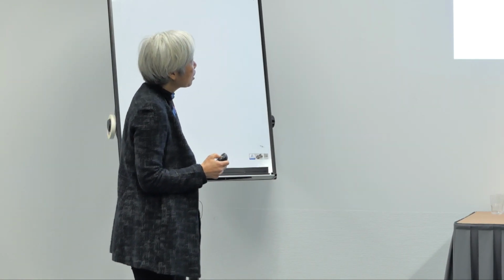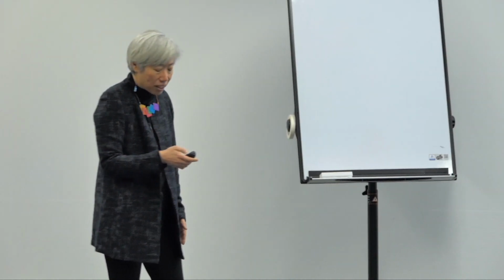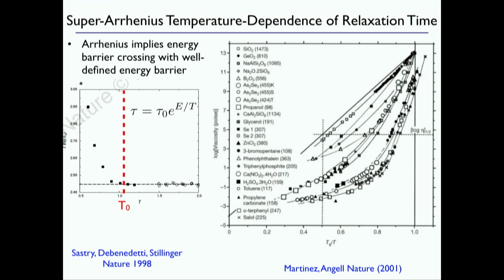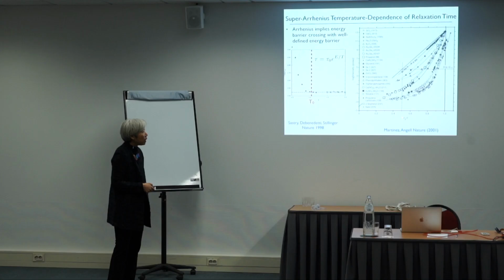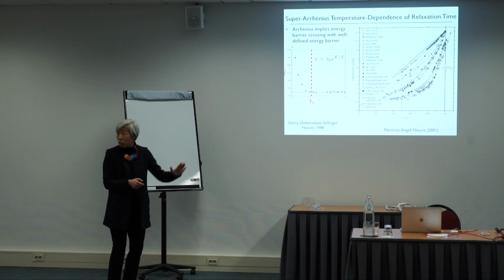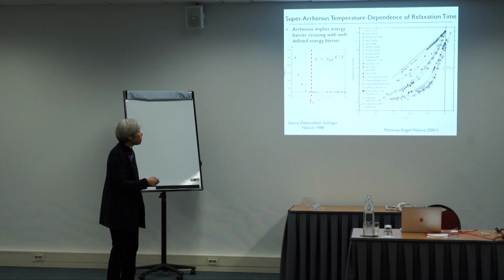All right. So let me just go through now a little bit more quantitatively what I said earlier. So this Arrhenius to super Arrhenius crossover at the onset temperature. If you look at, for example, this is the log of the viscosity, but it could equally well be the log of the stress relaxation time divided by the glass transition temperature over temperature. So if this were Arrhenius, it would be a straight line. This is the log of the relaxation time versus 1 over temperature. If it's Arrhenius, it's a straight line.